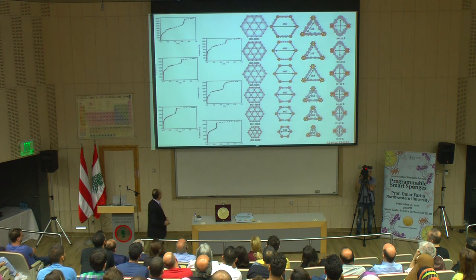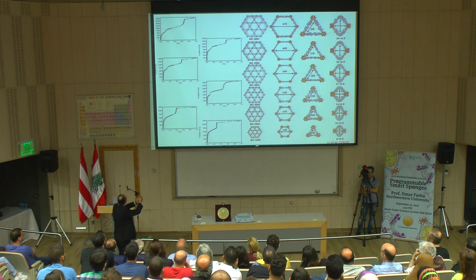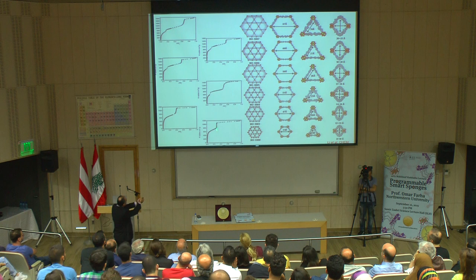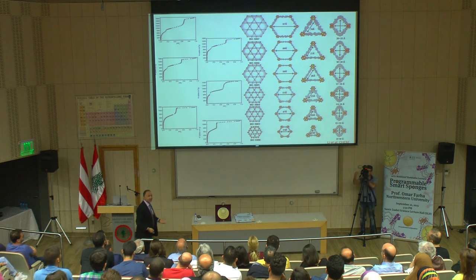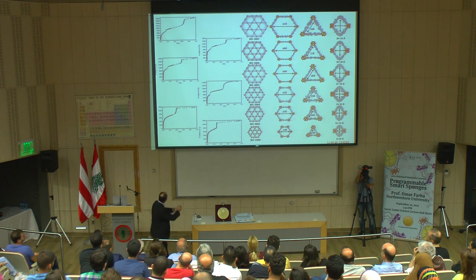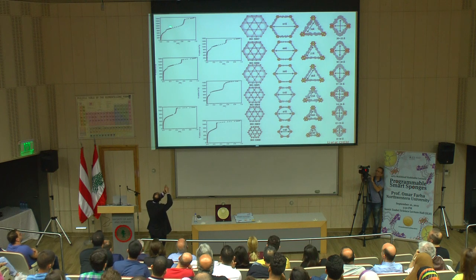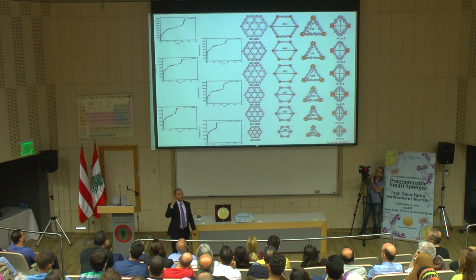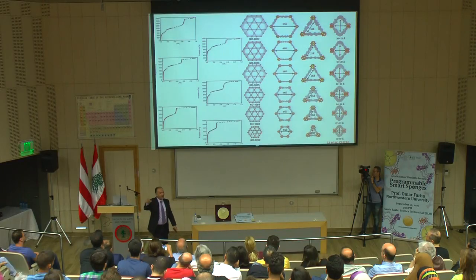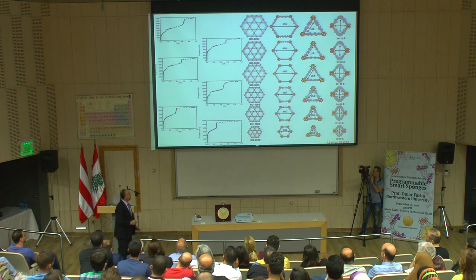Now, before we put the enzyme in, remember I told you about the step right here, which is a signature of a mesoporous material? After a while, you start to see two steps. Why is that? Because now the triangle and the hexagon are both in the mesoporous regime. And if you don't see that, that's a problem.